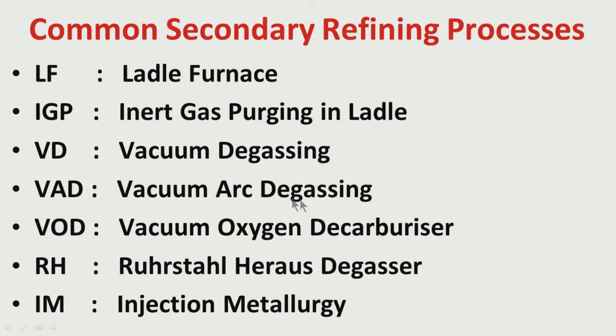Then I have talked about the vacuum processes. It may be vacuum degassing. Where degassing is possible, you create vacuum. We'll discuss today how it helps in degassing. Then we can have VAD, that is vacuum arc degassing. That means on top of vacuum, there is a facility of arcing. That means you can control the temperature. You can increase the temperature in the liquid bath, in the liquid steel. So, even if there is a temperature decrease during the process, it is possible to get back to the desired temperature using arcing.